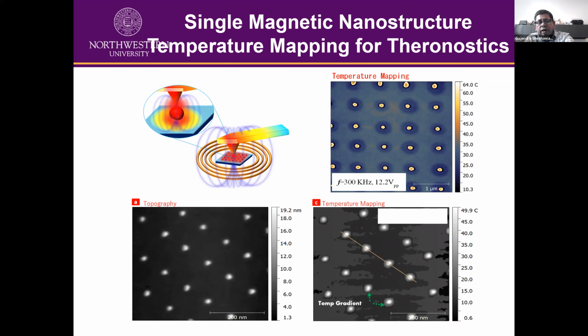And then you can see the bottom right image is basically the thermal temperature gradients in these structures. So you can map or measure the temperature of these individual nanoparticles. And on the top, in one of the experiments, we coated with polymers that can melt at 40, 50 degrees centigrade. And the particles are underneath it. So you can see here the melting of these polymer films when the particles are heated up. So it's pretty localized. You can individually heat these nanoparticles and use them for a wide range of applications for these materials.